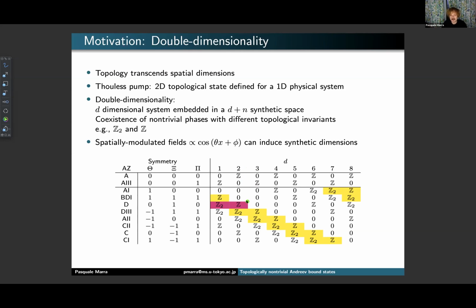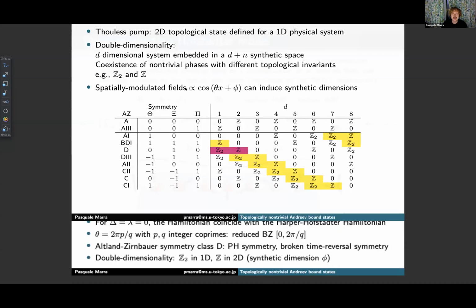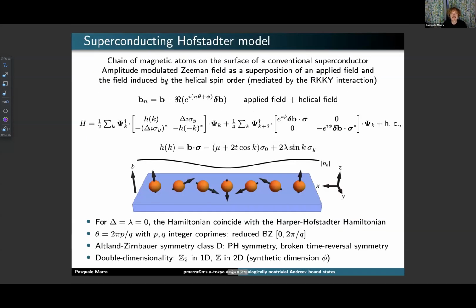So usually synthetic dimensions are realized when one has a spatially modulated field, like a harmonic modulation with a certain frequency and a phase offset phi. In this case, the phase offset behaves as a synthetic momentum, so a synthetic dimension. This system can actually be realized because, for example, one can have a chain of magnetic atoms on a conventional superconductor. So this is one of the realizations of a Majorana bound state system.